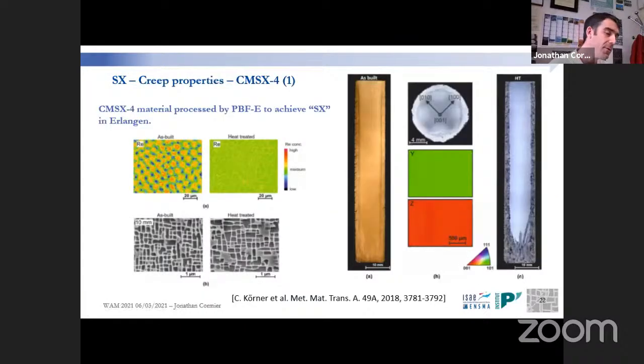Now I'd like to move to something really fancy. We are working in collaboration with colleagues of the University of Erlangen, and more specifically with the group of Carolin Körner. There are 2 groups on Earth able to grow almost single crystals. So it's not really single crystals. You can see here a specimen which has been processed by powder bed fusion electron beam. And with this optical observation, you can see this central part, which is almost single crystalline. And the strategy here is like for